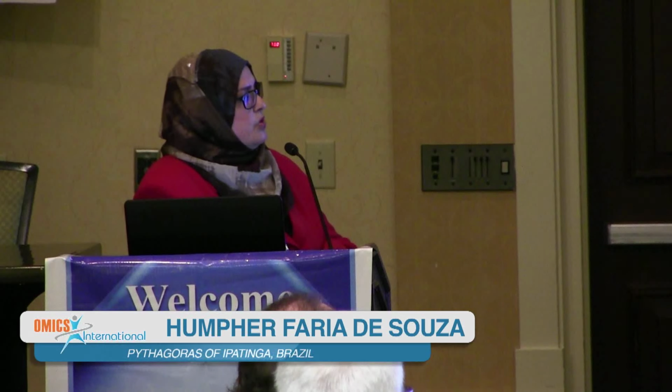Furthermore, we coated our particles with ApoE, covered with the green fluorescent coated ApoE. And what we did here, we incubated the BEnd3 cell line, which is a brain cell line. We incubated for 30 minutes with our particles, and then we used confocal laser scanning microscopy to detect the appearance of the nanoparticles on the cells.